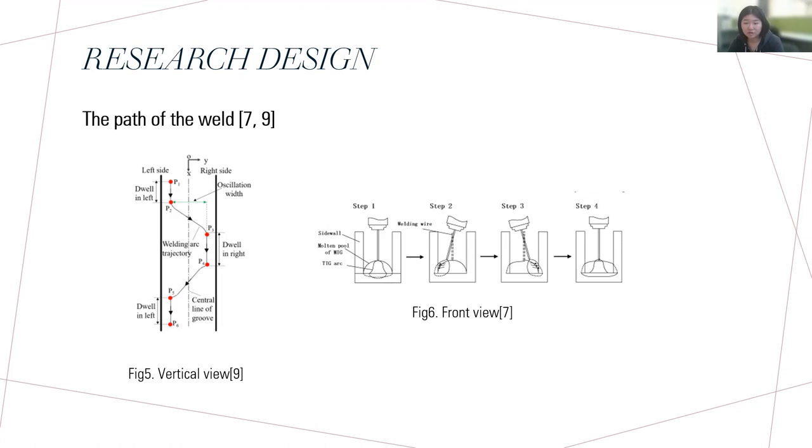To explore this, we conduct experiments with varied oscillation width, ranging from 0 to 4 millimeters with a fixed dwell time of 60 milliseconds.